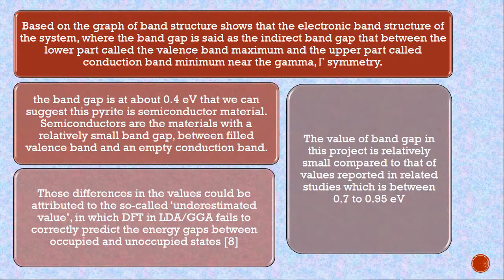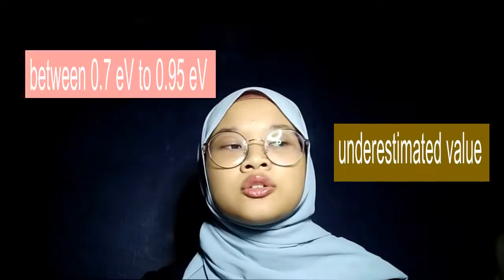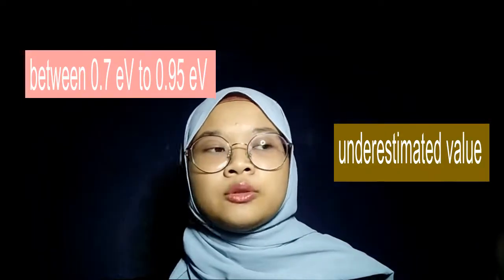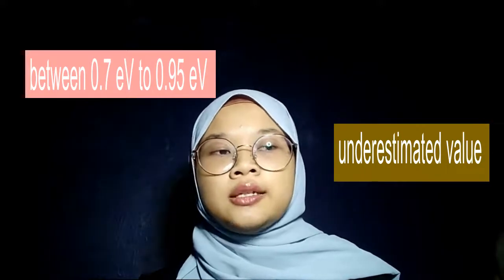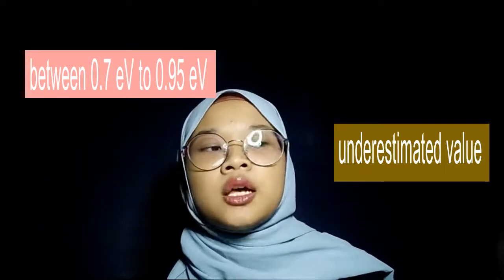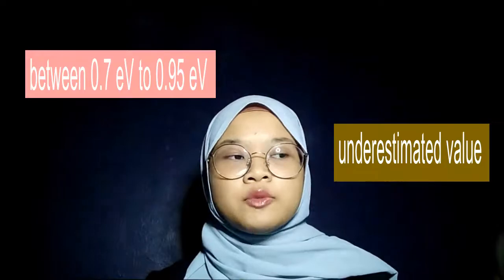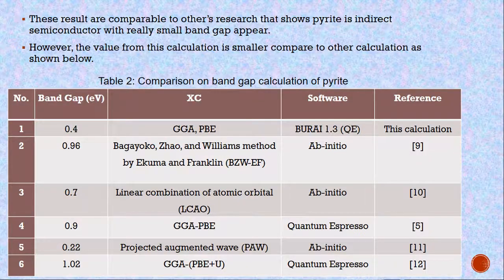This difference in the values could be attributed to the so-called underestimated value, in which DFT in LDA or GGA fails to correctly predict the energy gaps between occupied and unoccupied states. These results are comparable to other research that shows pyrite is indirect semiconductor with really small band gap. However, the value from this calculation is smaller compared to the other calculation as shown in table 2.